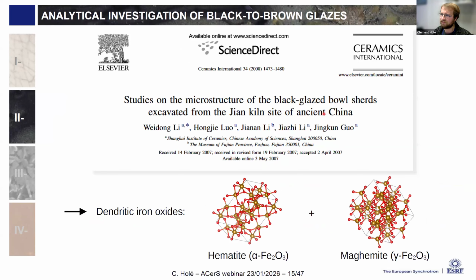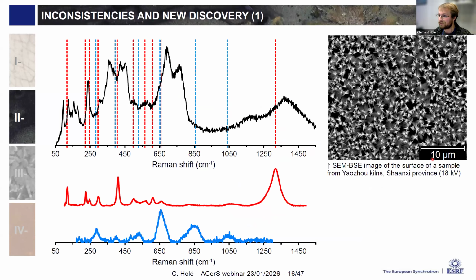One of the main analytical investigations made on this type of glaze in the early 2010s was the study from Li et al., where they analyzed several samples from Jian kilns using SEM and X-ray diffraction. They found that the microstructure of the brown areas was very typical, with dendritic iron oxides that they identified as a mixture of hematite and maghemite. However, later looks at this type of material showed a strong inconsistency. Here you can see the typical Raman spectrum recorded on these dendritic brown crystals. In red, you have the hematite spectrum, and in blue, the maghemite spectrum. You can see that they do not correspond at all. So it might actually be something else.